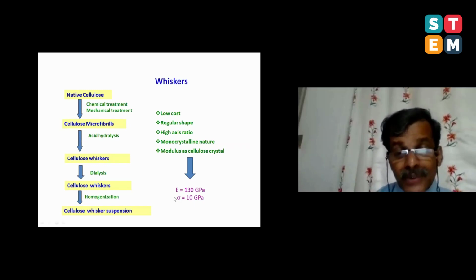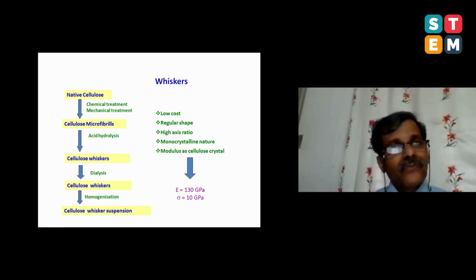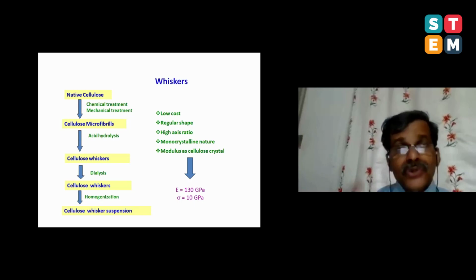And the beauty of this material is, look at the Young's modulus of this material, 130 gigapascals. And strength is 10 gigapascals. It's an exciting nanomaterial. I would say one of the most interesting nanomaterials as compared to carbon nanotube or graphene. It's a very interesting material: low cost, regular shape, high aspect ratio, crystalline. There are lots and lots of positive points for nanocellulose.